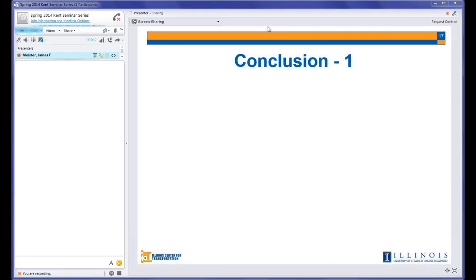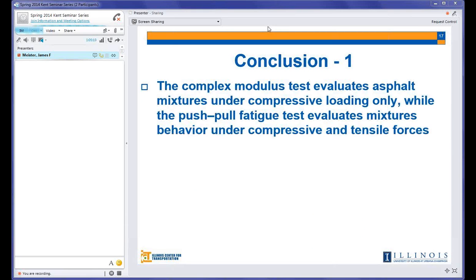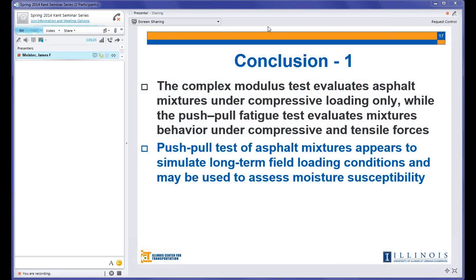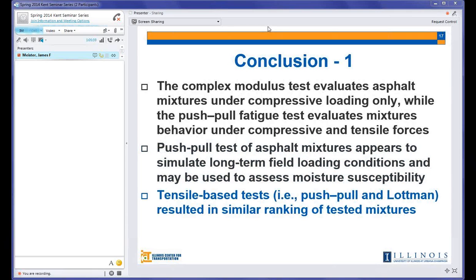Okay, so the conclusion at the end: complex modulus, as mentioned, evaluates the asphalt mixtures under compressive loading, while the push-pull does that under cyclic tension and compression forces. The push-pull test appears to simulate the long-term field loading conditions, and it can be used, as shown, at least for our three mixes to assess the moisture susceptibility. The tensile-based tests, because we have tension failure in both tests, the Lottman and the push-pull, result in the same ranking for the three mixes.